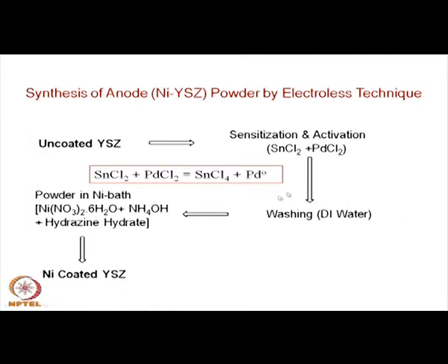Here we are not randomly mixing the two phases together, but in a structured manner. In a structured manner, we are putting the nickel coating on the individual powders. So, that is possible by this powder electroless technique.